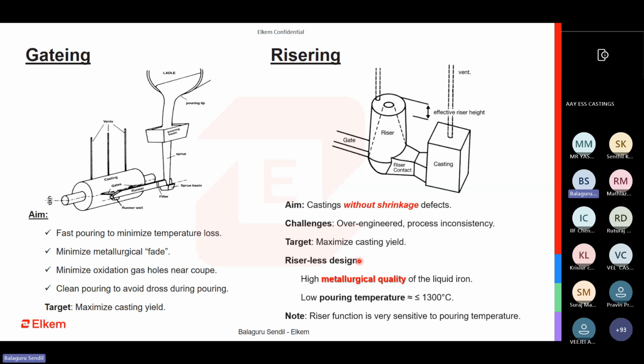I would touch upon this with our inoculation and nodularization topics. And at the same time, the temperature must be not more than 1300 degrees Celsius. So to have this sort of targets, which is going to be the future of ductile iron foundries in India, to be effective and competitive in the market, we need to have a shift in our mindset: do we really need to use a bigger riser?